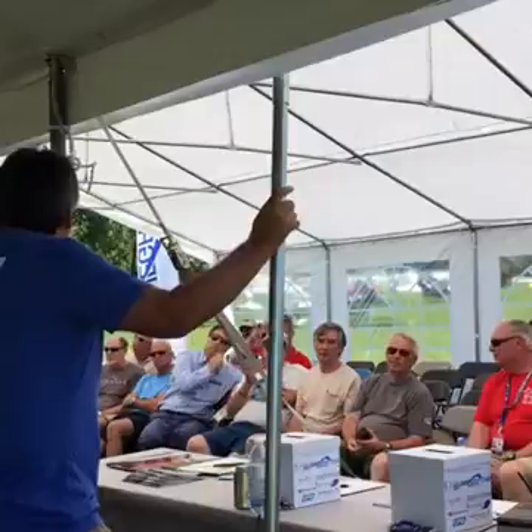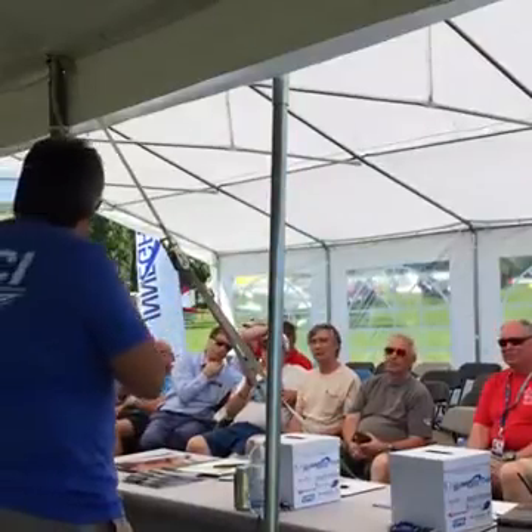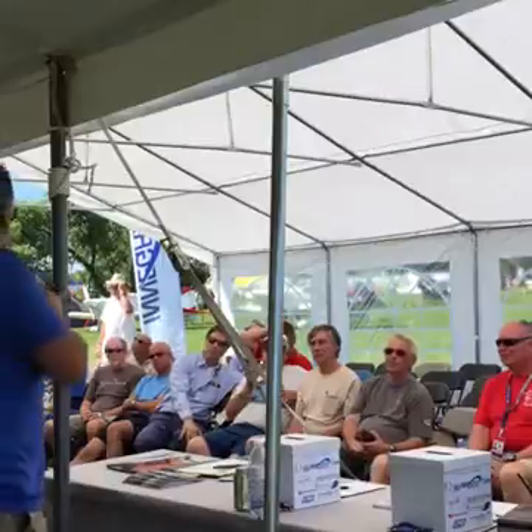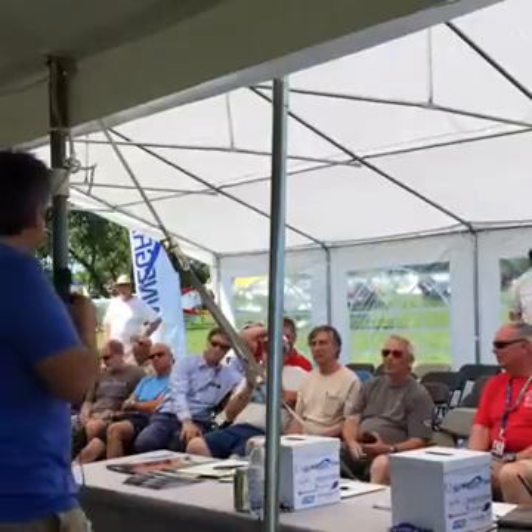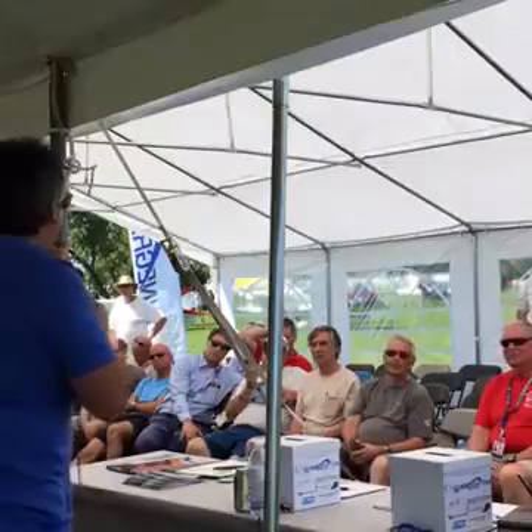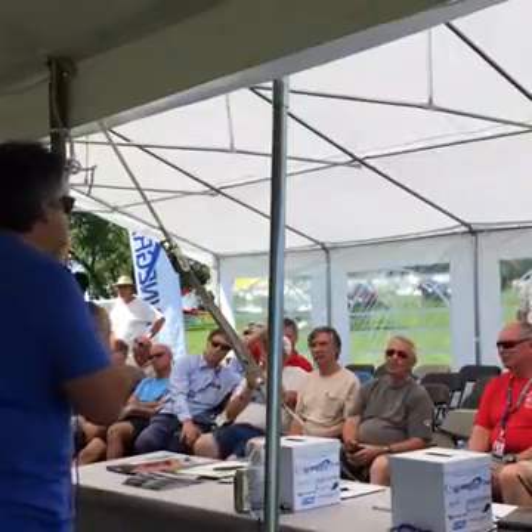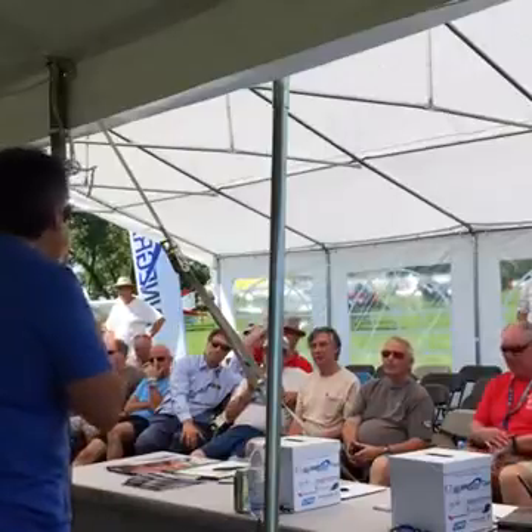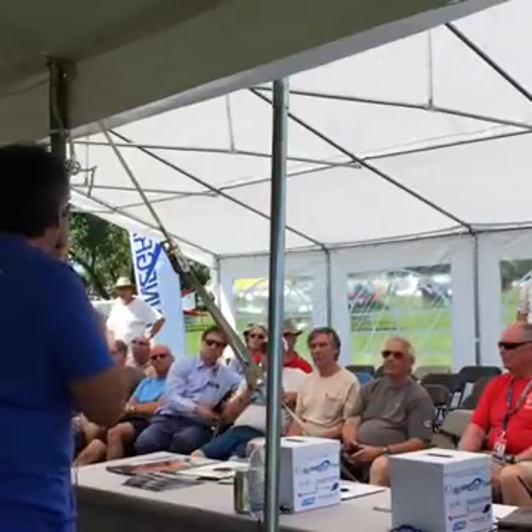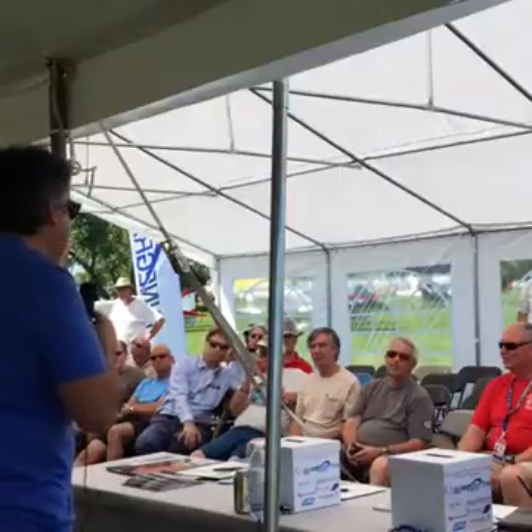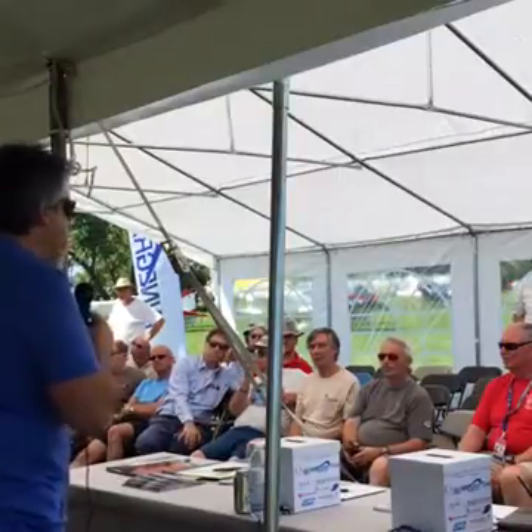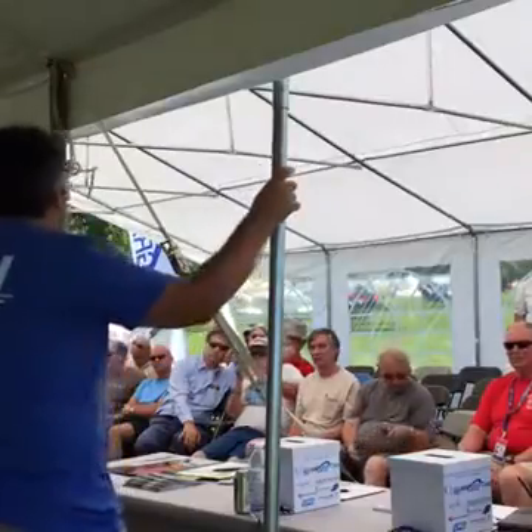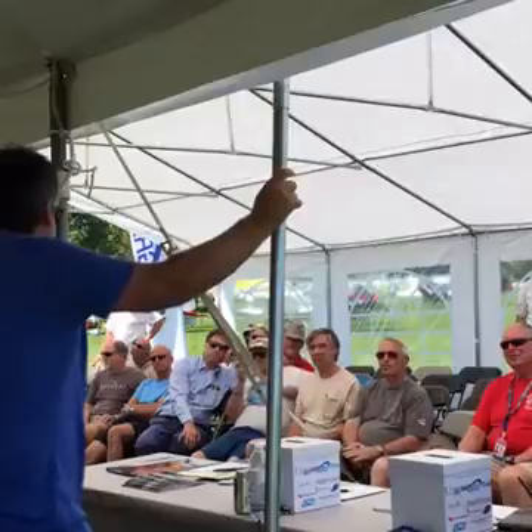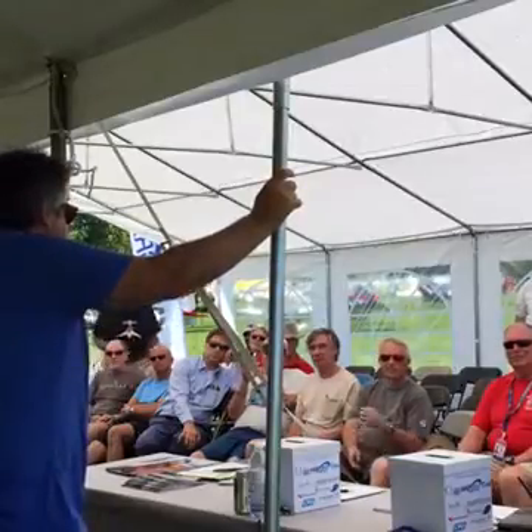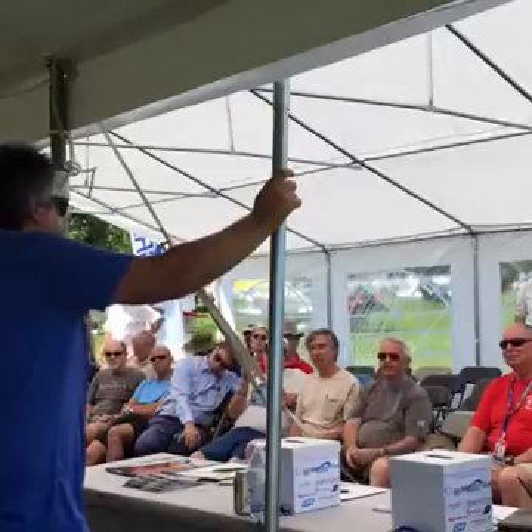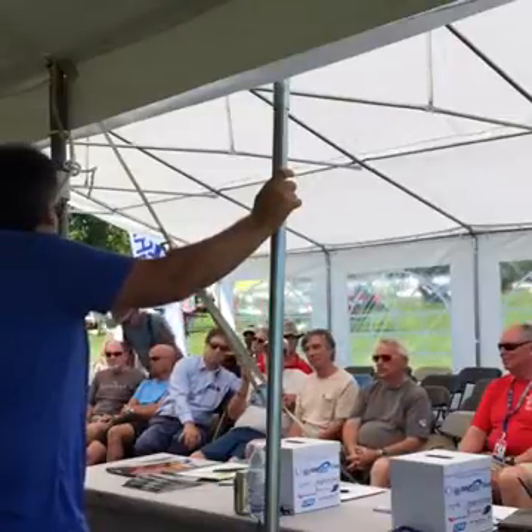How about viscosity? Viscosity for this resin right now we're at 200. This is about 200 to 250 centipoise. Epoxies, the base resin for an epoxy will be around 1600 centipoise, and then when you put your amine into that, depending on what amine you use, you're probably going to be around 1000 centipoise. So this is going to be a much thinner product. Great for infusion. It was designed with infusion in mind. We've done large boat hulls with it. We did an airplane last year. It belonged to Tony. Those of you who were here and saw it demold, it came out really nice. It was a beautiful part. So we've had great luck with it.